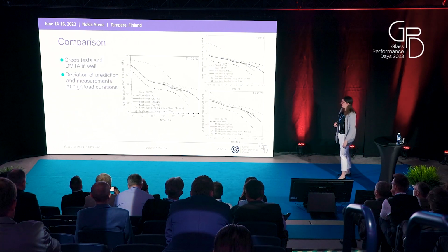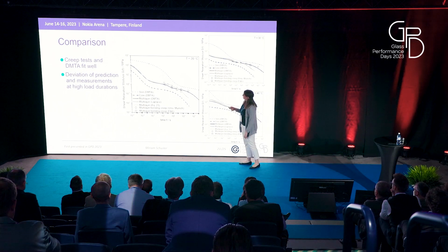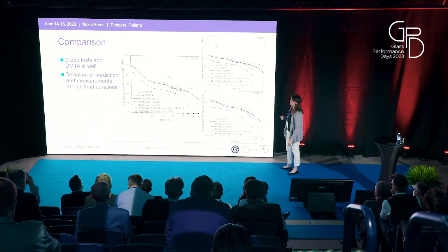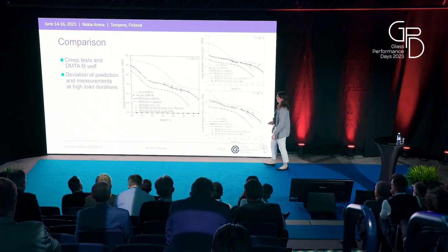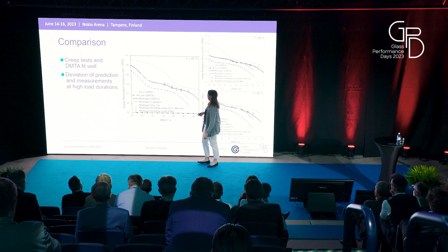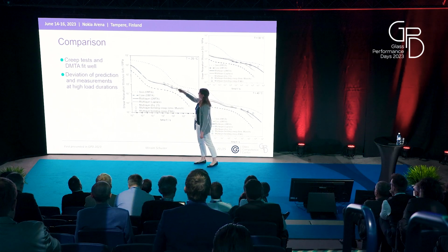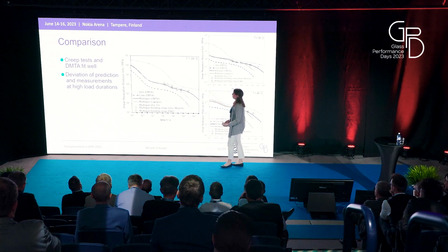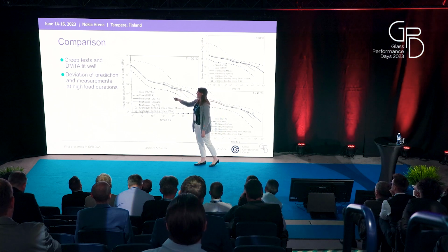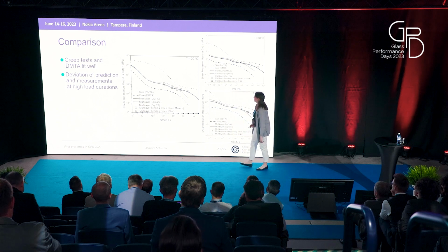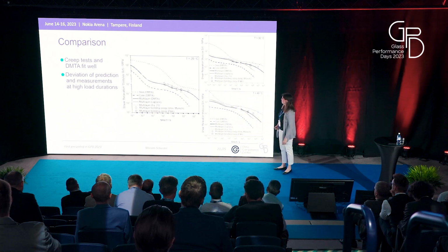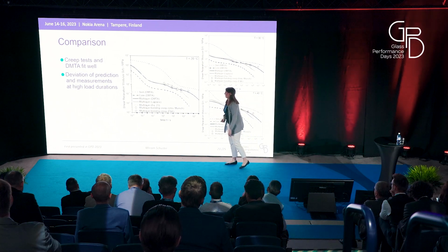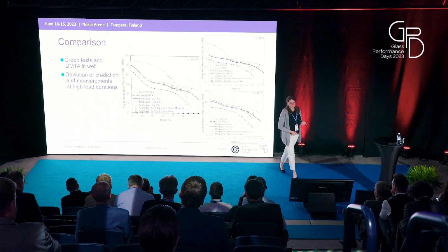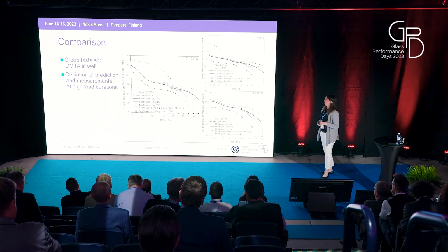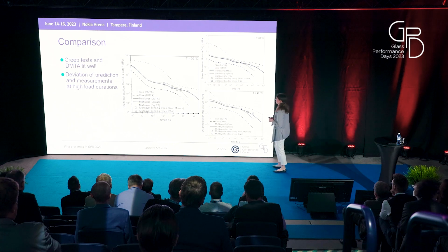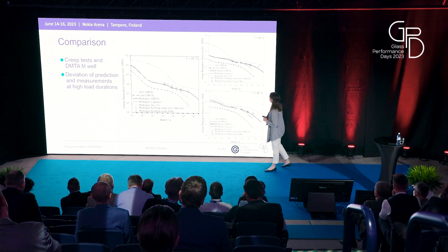And here we see the results. So again, or maybe first, we have three graphs. The first one is at 20 degrees Celsius, then 30 and 40 degrees Celsius. We have the master curves, or the evaluated Prony series for the skin layer, the dotted line, the core layer, which is the dashed line, and the master curve obtained from DMTA for the multilayer, which is the black continuous line. Then we see the symbols. We have the circles and the squares, which are the results from the creep tests. And we have the gray lines, which are the predictions. So two different predictions were used. The one using the Laplace transformation and the simplified rule of mixture prediction. And first of all, we see that the creep test and the DMTA results fit quite well for all the temperatures.